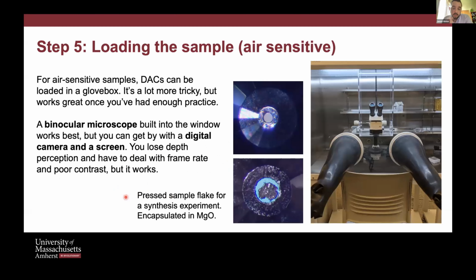You can also do this in a glove box. You know, this ramps up the difficulty somewhat, but it's absolutely achievable. Just requires practice. You've got to put in the work to get good at this. But you can do all of this in an inert atmosphere. That's no problem. The tricky part is getting the pressure medium in. I'm not going to go into too much detail on that, but you can do all the sample load, and you can close the cell up in a glove box and keep it completely oxygen free.